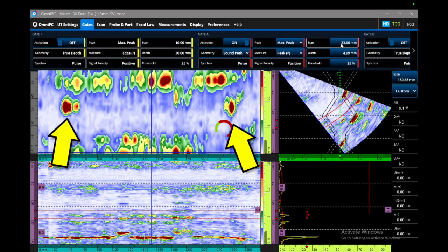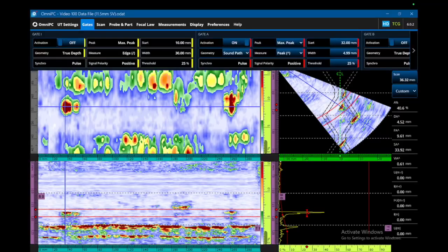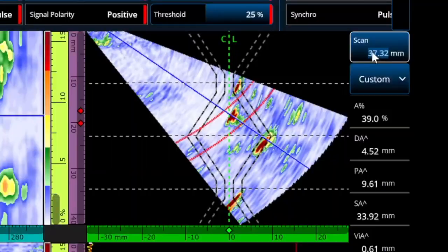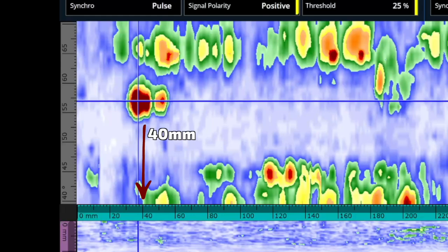There's one here at the beginning and one at the end. I'll double click on the C-scan down to the first one — you can see it's something volumetric. If we take a look at the S-scan right there, it's definitely bright red, so we know it's over 20% reference. I'm not sure what it is — I'm going to guess that it's slag at this point. I'm really just writing stuff down. I'm going to write down 40 millimeters roughly on that one.